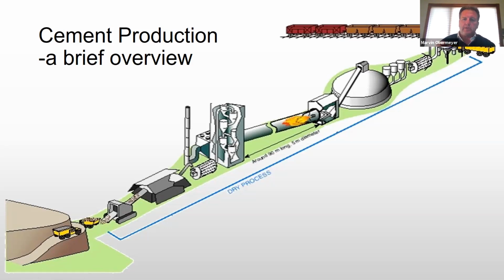Kilns range in size between, let's say, 200 feet to 500 feet long and 15 to 20 feet in diameter. They are at an incline so that the material tumbles down toward the heat of the kiln. The flame of the kiln is at the business end, the south end, the lowest end of the kiln, of course. That flame is approximately 40 to 50 feet long, maintaining a temperature at approximately 2,600 degrees Fahrenheit. So it's an enormous amount of heat.